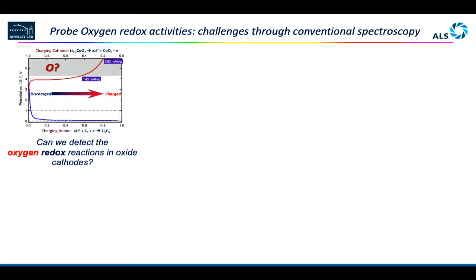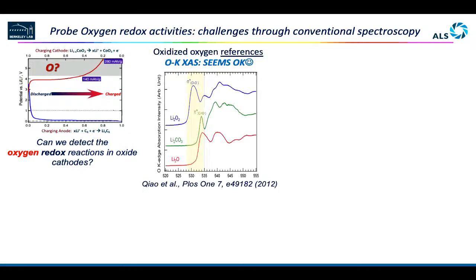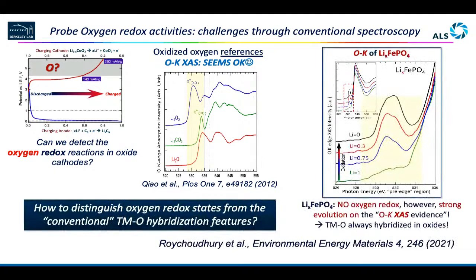So it's very important to figure out what's really happening when you go to the high voltage, and of course to understand why it doesn't work. Again, on the absorption, if we look at the reference compound, it is seemingly promising, because if you compare the oxide state with the peroxide state, you do see, especially in the pre-edge regime over here, the peaks sitting at very different energy. However, if you look at a transition metal oxide, that's a whole other story, because everyone here will know the pre-edge regime in exactly this energy range is actually dominated by the 3d character through hybridization. And at that moment, we called it a killing experiment that killed tons of papers, because many papers were discussing the pre-edge change of the oxygen K-edge to claim, oh, oxygen is going through a redox process, but it's really just a hybridization effect.